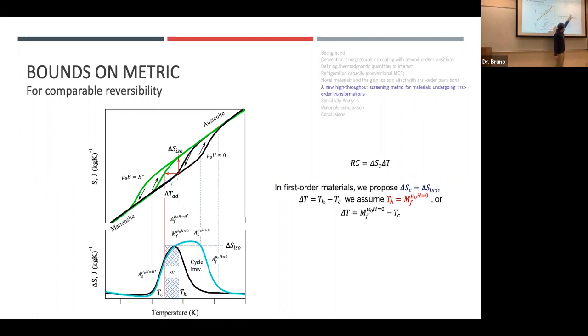Before, the delta S at the cold source is now going to be just the isothermal entropy change, which is the difference between austenite and martensite. We need to assume that the hot temperature reservoir is our martensite finish temperature for the reversibility. And sort of the width of the block is our adiabatic temperature change.